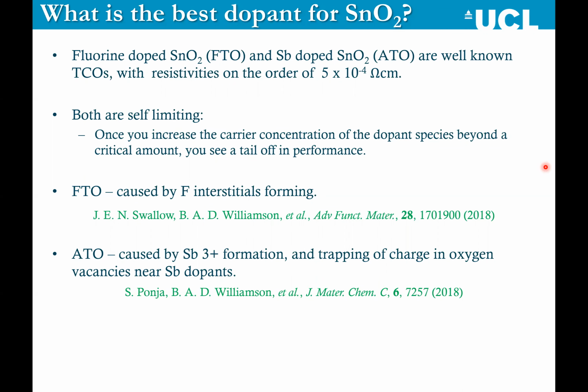The main dopants used in tin dioxide are fluorine, so FTO, or antimony, so ATO. And you can get pretty low resistivities, but both of these dopants are actually self-limiting. As you increase the carrier concentration, beyond a certain carrier concentration, you start to get a tail off in performance. And nobody had actually understood well what was going on in these systems, despite using them for over 50 years. So we did some analysis and we showed that for FTO, as you increase the carrier concentration, you actually start to get compensation by fluorine interstitials. And for ATO, you get Sb3+ formation because antimony 3+ segregates to the surfaces. And also you can get trapping of charge in oxygen vacancies near to antimony dopants.